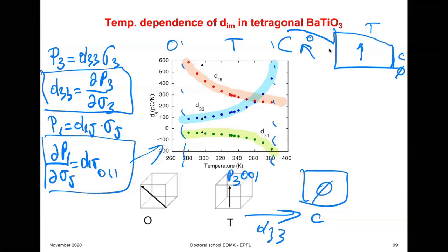Eventually, once we go to phase transition, it will disappear. The polarization will become 0. And this means that we have here pre-transitional behavior. The coefficient feels what will happen with the polarization even before polarization becomes 0. The coefficient feels that polarization must become soft to changes along the X3 direction, because it will go from here into 0.